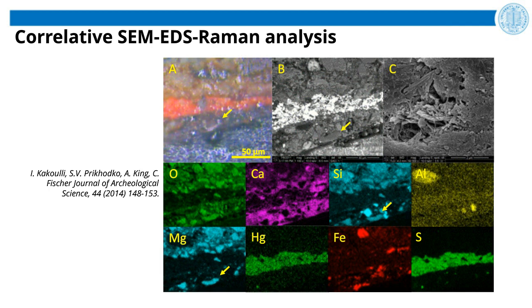The optical image shows the stratigraphy of the painting with the following layers. The easiest to recognize is the bright red cinnabar, and it shows a high concentration of mercury and sulfur, which is quite consistent. We also see some inclusions which are rich with calcium, oxygen, magnesium, and silicon, and specifically some inclusions which are rich with magnesium and silicon. It was a first suggestion that it might be asbestos,